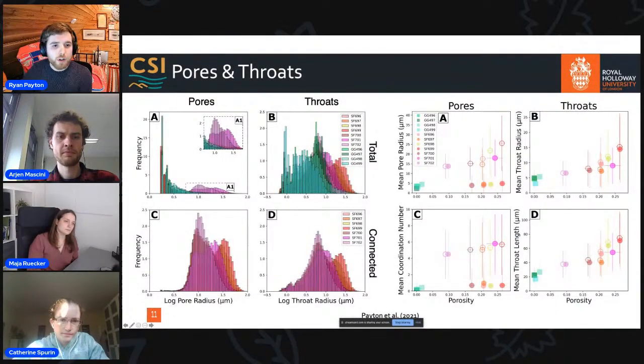And we can then make measurements from there to further characterize the pore structure. So if we have a look at these plots on the left-hand side to begin with, at the top here, what we've got is pores down the left-hand side and throats down the right-hand side. And the top two are for total porosity and the bottom for connected porosity. So what we're seeing is that in the total porosity, there's this large portion of very small pores, which can be explained by those intragranular pores that I just showed you, because these aren't contributing to connectivity at all. Down here, where we look at the connected case, all of these smaller pores are lost. So it really is the larger pores which are contributing to the connectivity.